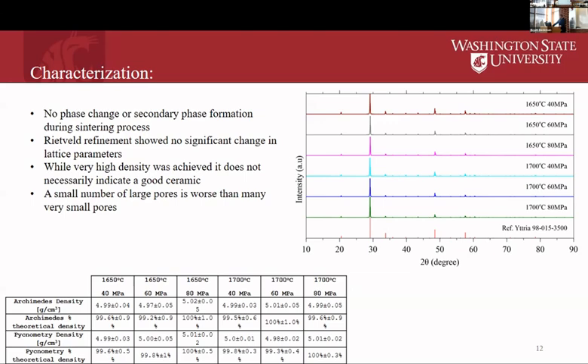What's interesting is the nominal density of yttrium oxide is 5.01 grams per centimeter cubed. Usually what I've heard is if you get above 99.5% density, you're usually in the sweet spot for when your optical properties start to become relatively good.